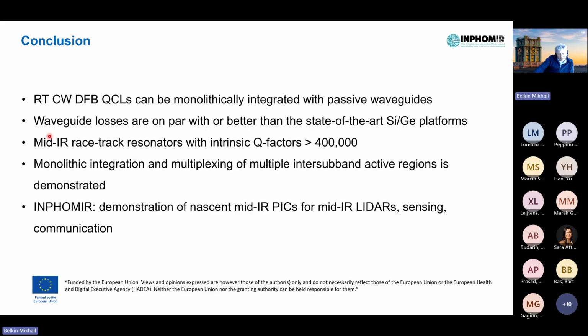So in conclusion, I've described to you this nascent field of mid-infrared photonic integration. I showed you that DFB QCLs can be monolithically integrated with passive waveguides. Waveguide losses are similar or even better than state-of-the-art silicon germanium platforms. High Q ring resonators can be demonstrated at 5 microns, but also at longer wavelengths. Monolithic integration and multiplexing of multiple intersubband active regions can be done.